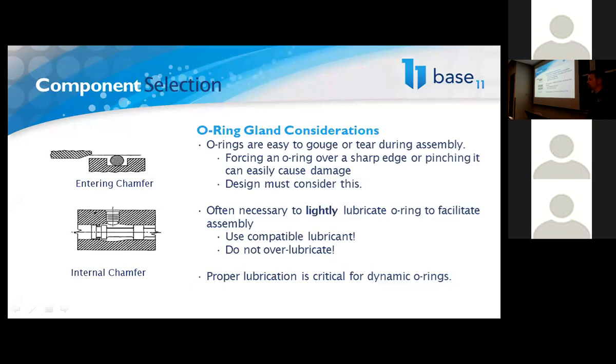It's also generally common practice when you're installing O-rings to lightly lubricate them. There is going to be a certain amount of friction as the O-ring is installed and as it slides past whatever component it's going to be sliding past. And so proper lubricant always helps with that. It's important not to over lubricate, and it's important to always use a compatible material. If you've got too much lubricant, that can squeeze out and that can migrate other places in your system, which you generally don't want.